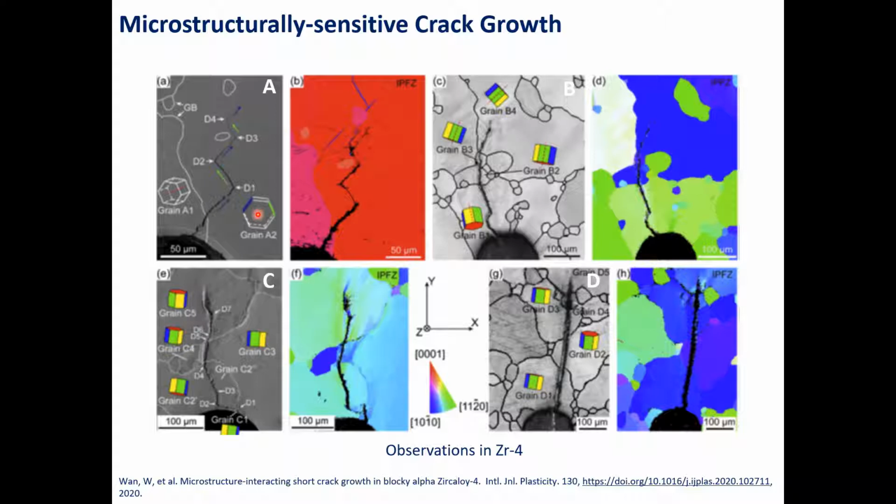But in addition, the cracks growing in these two scenarios, this grows much more rapidly than this crack. So the planes upon which this is growing are such that the cracks, for one reason or another, have a much higher rate of growth compared to this. To some extent, it's related to the ductility, because in this orientation of the crystals, we do see an awful lot more plasticity. And so it must be related to that, and the drivers of the stored energy density, potentially local to the crack tip as it grows, will be different because of the differing microstructures. And these are the things we hope to be able to capture with our stored energy: the oscillations and also the rates of growth.